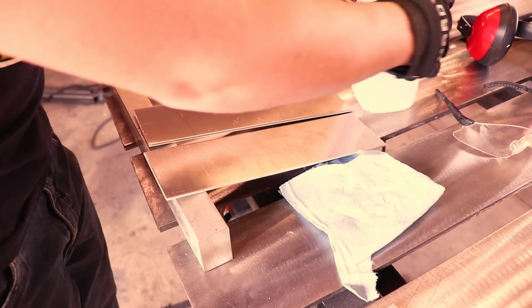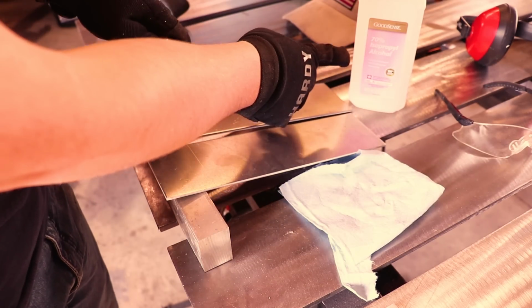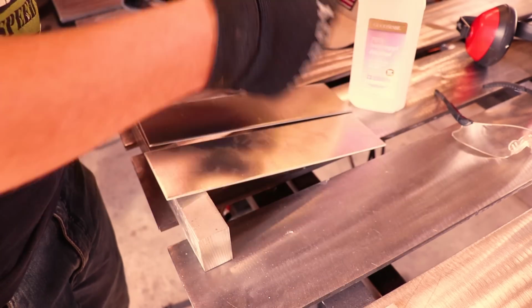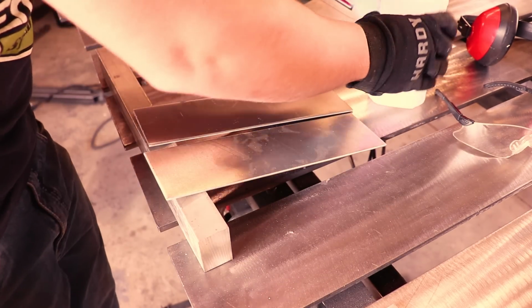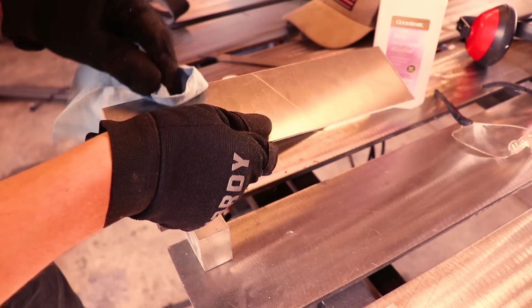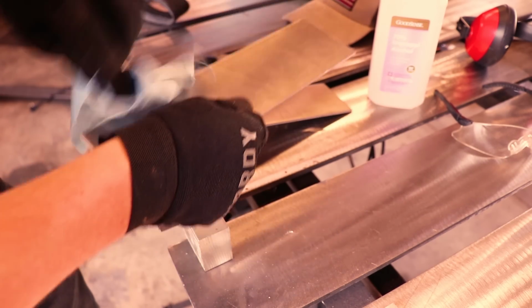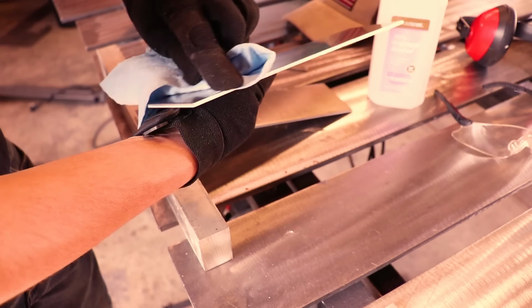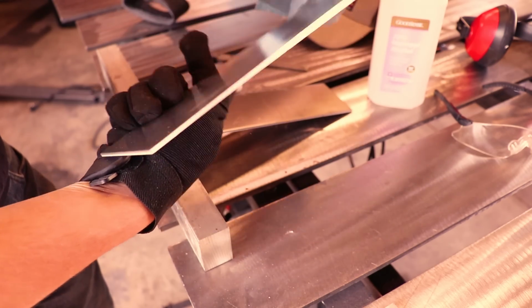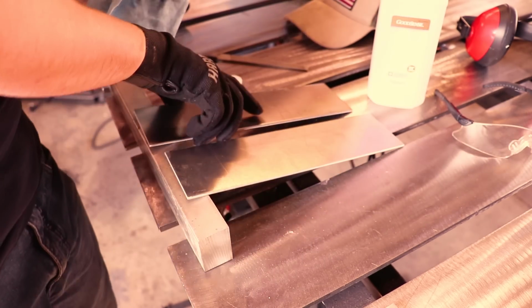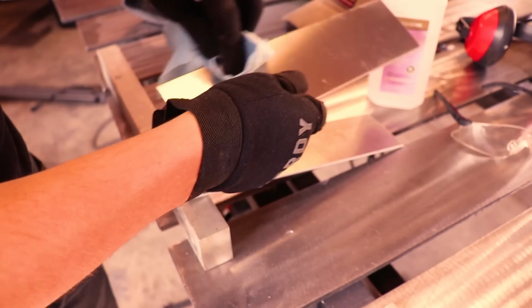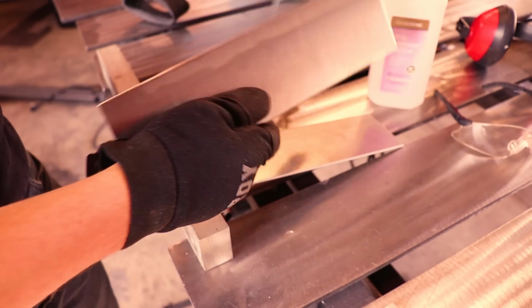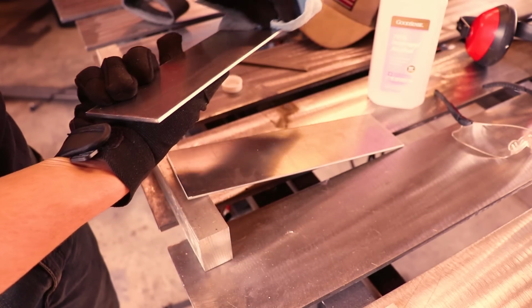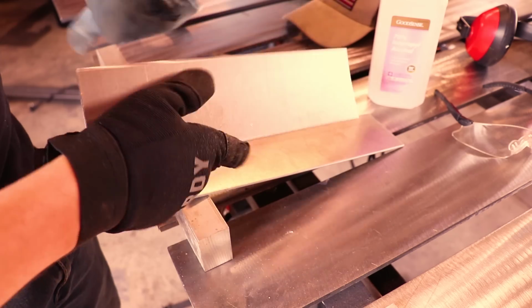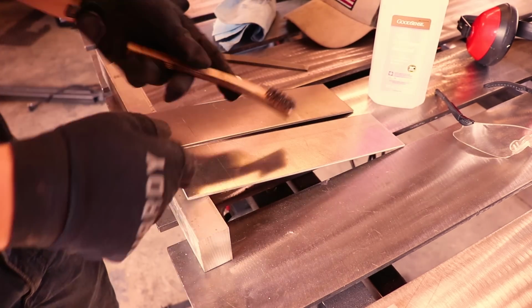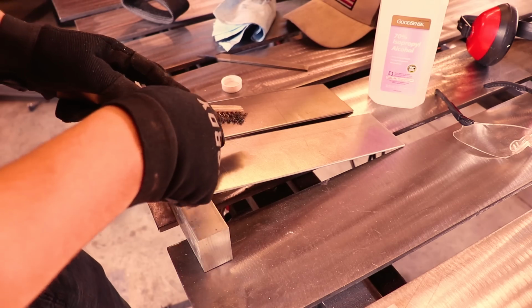Now I'm going to wipe them down with 70% isopropyl alcohol. Don't use that 90, it leaves a film on it. So I'm just going to wipe it down, just basically where I'm going to be wire brushing. And this gets all the stuff on the surface off, so that when you're using your wire brush, it doesn't embed the material down in there.